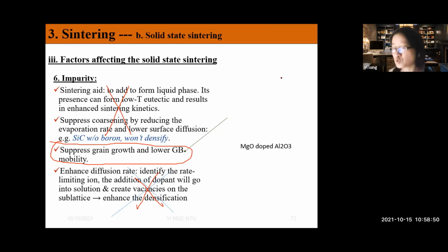You always quickly densify first, forming a very dense structure with grain boundaries first. Then later you can relax and let grain growth happen. This will help you have a very good density, instead of the grains becoming very big at the very beginning. That's correct, right?